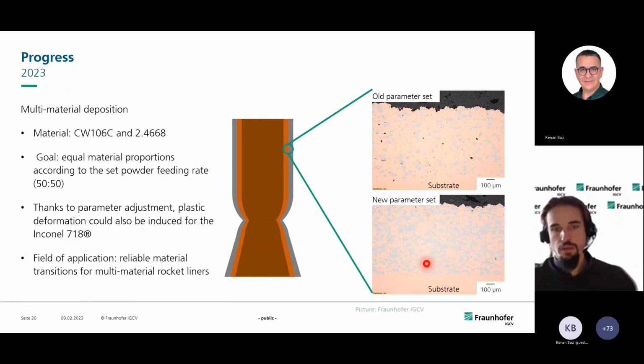So why is this important? Because when we are building up a rocket liner, we want a sufficient or a reliable material transition from copper chrome zircon to alloy 718, and that's why we first want to spray copper chrome zircon. Then we want to spray the mixture of both materials, and afterwards pure alloy 718. And this multi-material here means especially the continuous material transition, as I mentioned within the introduction.